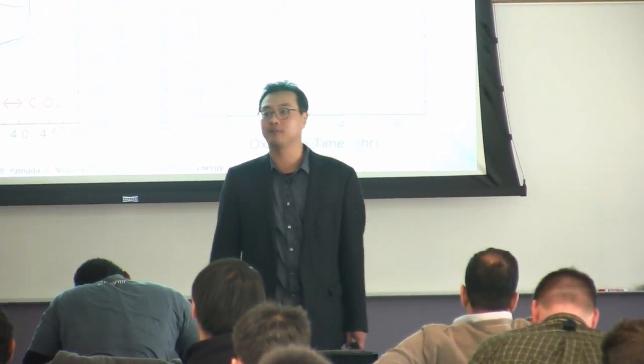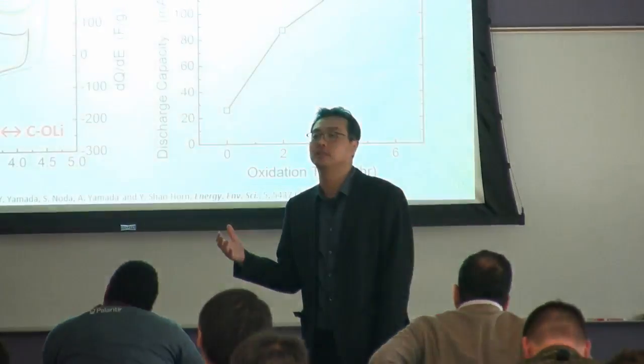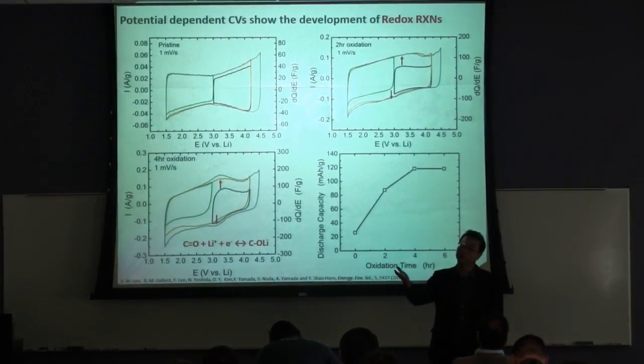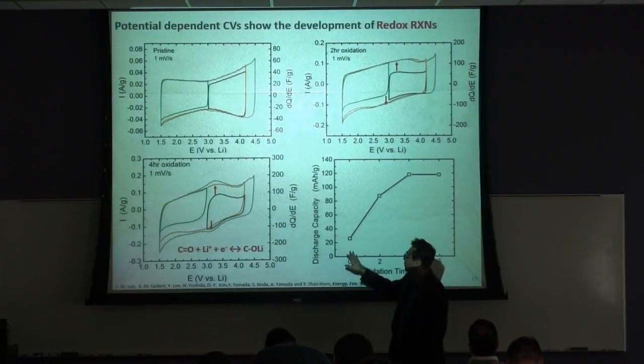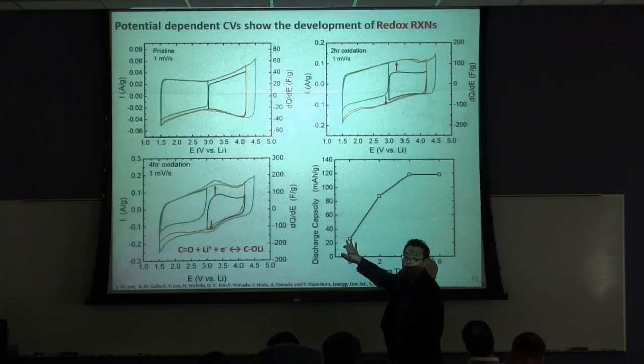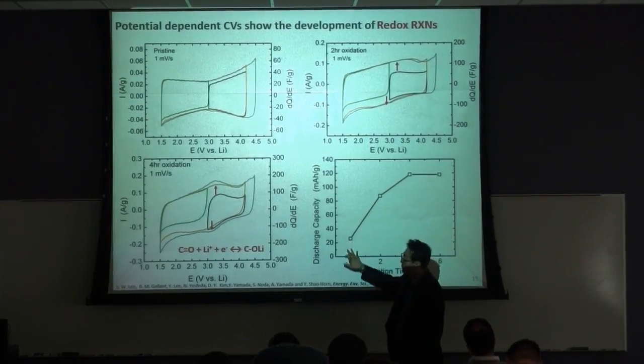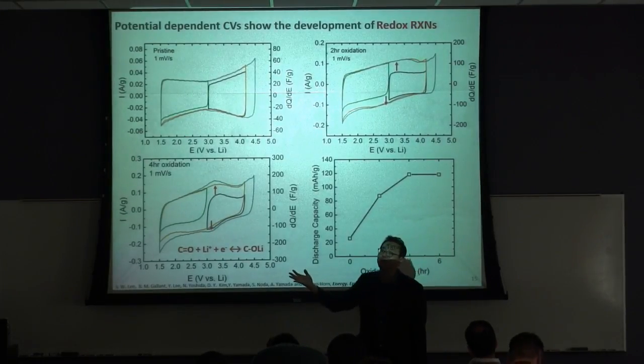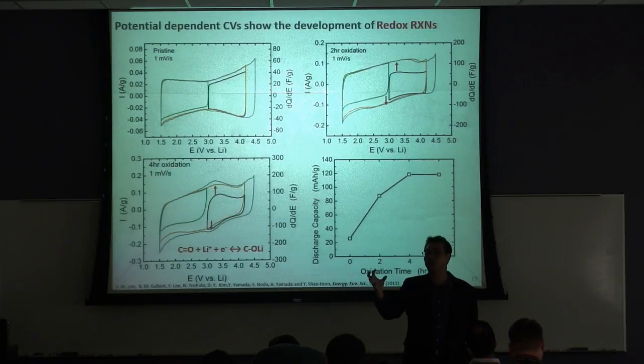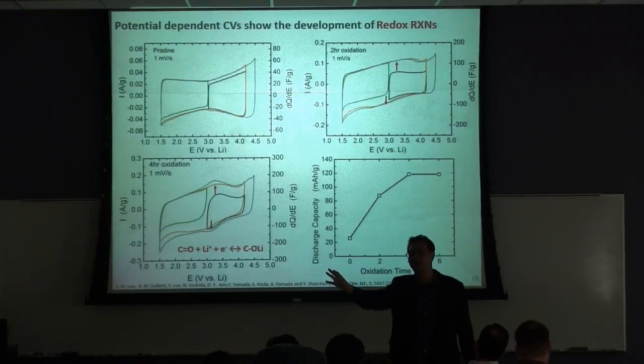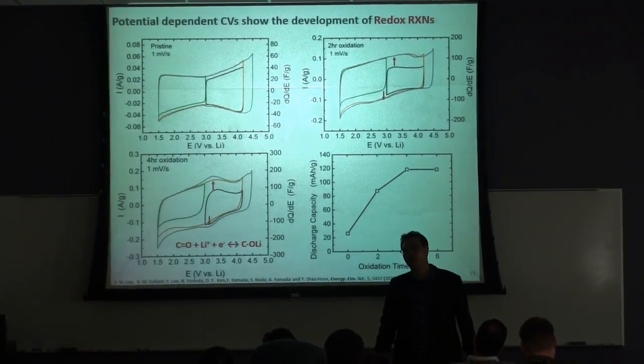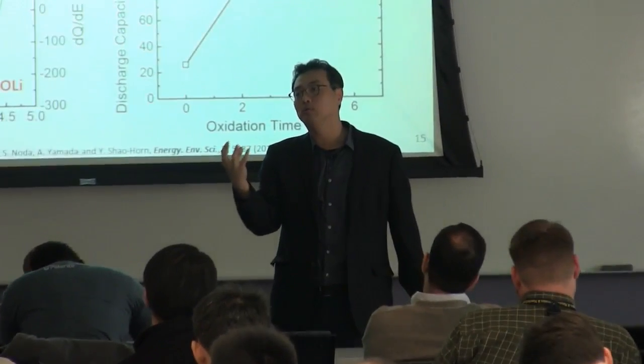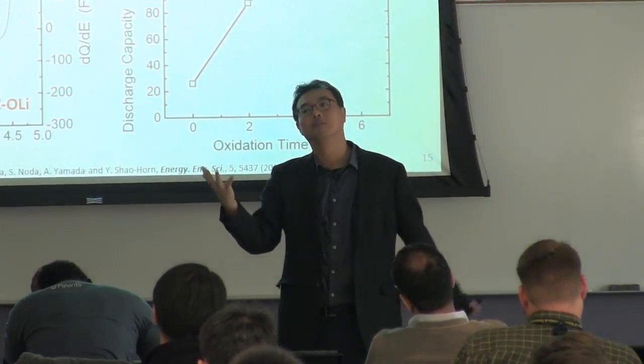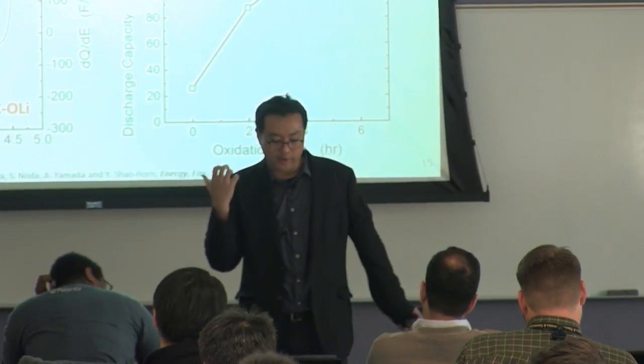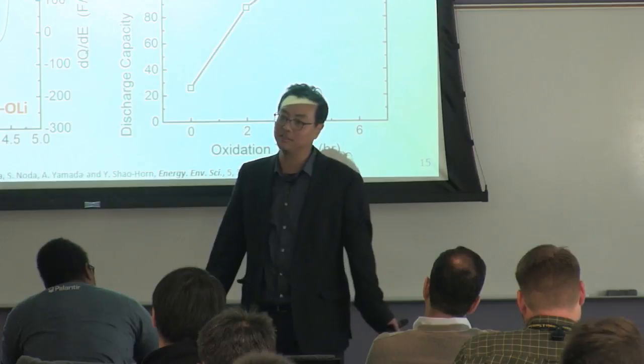First of all, as you expect, there are two types of charge storage mechanism, right? The first one is the double layer capacitance, as you mentioned. That's related with the surface area. The other one is the pseudo capacitance, or surface redox reaction between the oxygen functional group and lithium-ion. If you see, this pristine carbon nanotube shows only 30 milliamp hour per gram. So this can probably represent the double layer capacitance portion. But after oxidation, it becomes 120, sometimes 150. So you can roughly estimate the contribution of the double layer capacitance and surface redox reaction. Based on this result, double layer capacitance is probably below 10 or 20%. As you mentioned, there might be loss of some double layer capacitance, but we have more oxygen functional group. Because we are incorporating more surface redox reaction, we can increase the overall energy density.